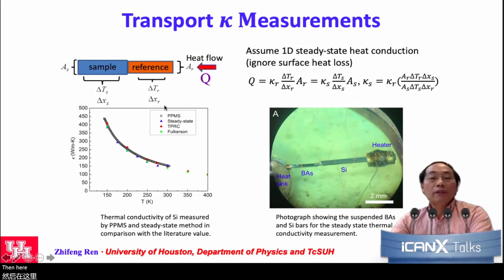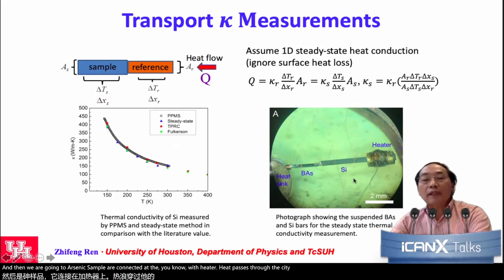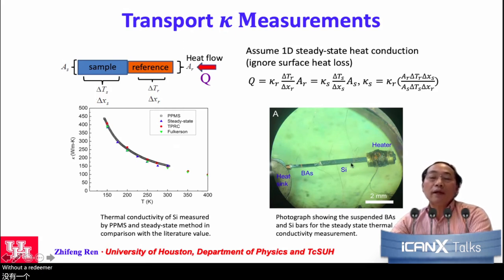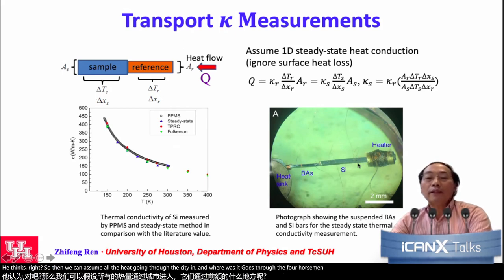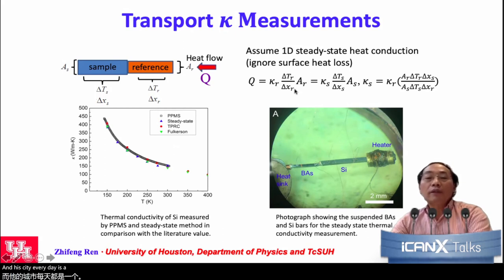Here we use a reference sample, silicon, which has a characterized thermal conductivity. Then our boron arsenide sample is connected, and you have a heater, and heat passes through. It sits inside a vacuum chamber without radiation heat loss, and the temperature is kept very low, so the hot side is not much different from the heat sink side. Then we can assume all the heat went through the silicon and also through the boron arsenide. Everything about the silicon is known, and then we can calculate the sample thermal conductivity.